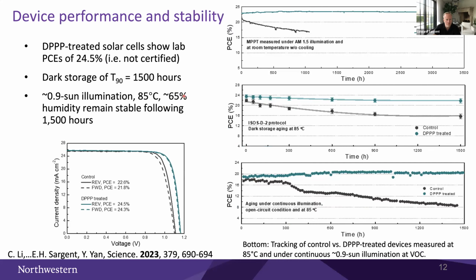So this correlated with interesting device performance. I think I'll highlight in particular the power conversion efficiency after aging under open circuit conditions in this case, but at quite a high temperature of 85 degrees C. And you'll see devices here that sustained about 1,500 hours of impressive performance.